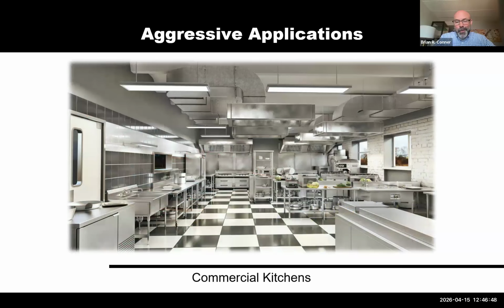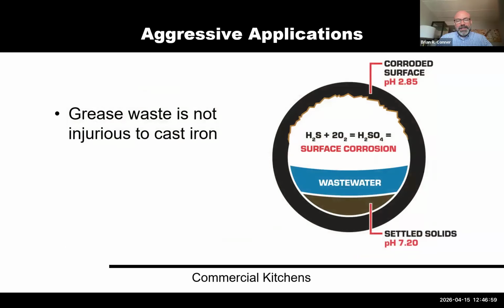Also, within hospitals, you've got commercial kitchens. And anywhere there is a commercial kitchen, there is a chance for corrosion. The reason is that grease waste itself is not injurious to cast iron, but the sewer gases and the hydrogen sulfide gas created by solids being left behind, especially in commercial kitchens, can be extremely corrosive to metallics, all metallics. And so they're using aggressive cleaning chemicals and putting less water into the piping system.